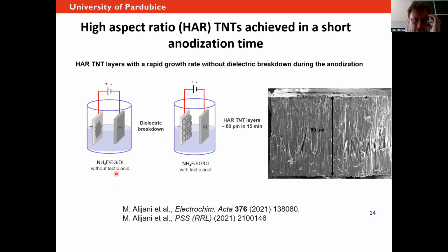But if you do insert lactic acid in the electrolyte, you can actually go much higher with the voltage. So you can apply, for instance, 140, 160 volts, which is quite a lot. But this gives you extremely high currents that you can maintain for a relatively short time. So in principle, suddenly by using high voltage, you can anodize only 15 minutes or even less, and you have, as you can see here, almost 80 microns, if even more.